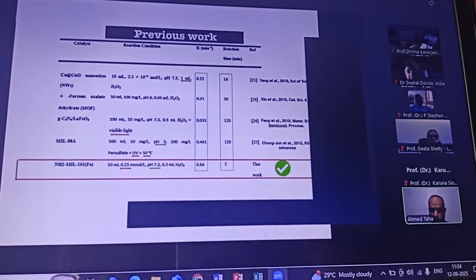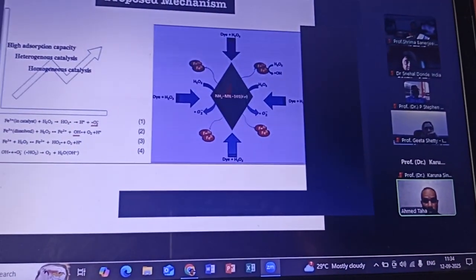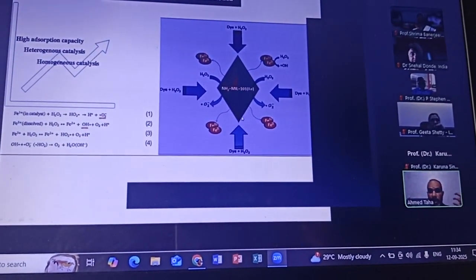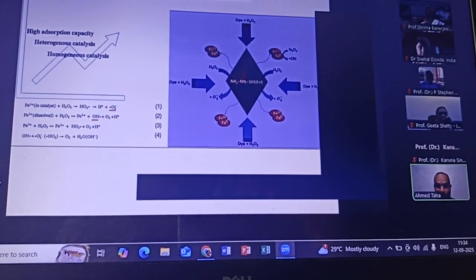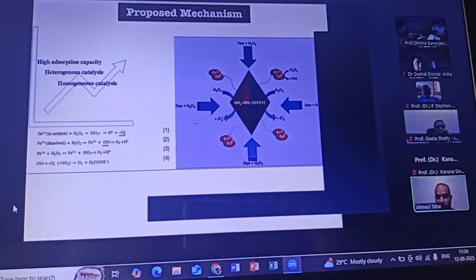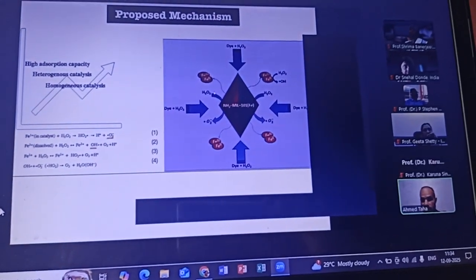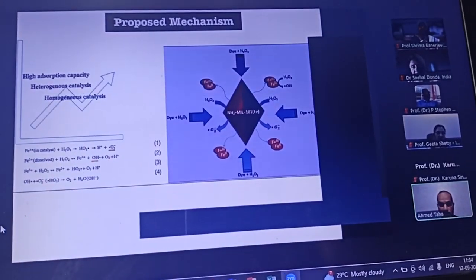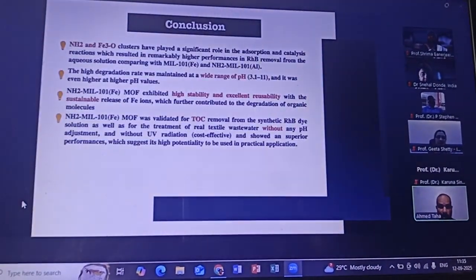And we compared our work with other people's, and we found we actually have better performance compared with other reported materials in similar applications. So the material has a good ability to absorb the pollutant on the surface, and that gives a very good advantage to let the catalyst break it down within the Fenton reaction on the surface and within the media, with the iron leached into the water. So that is the reason we had a very excellent performance.